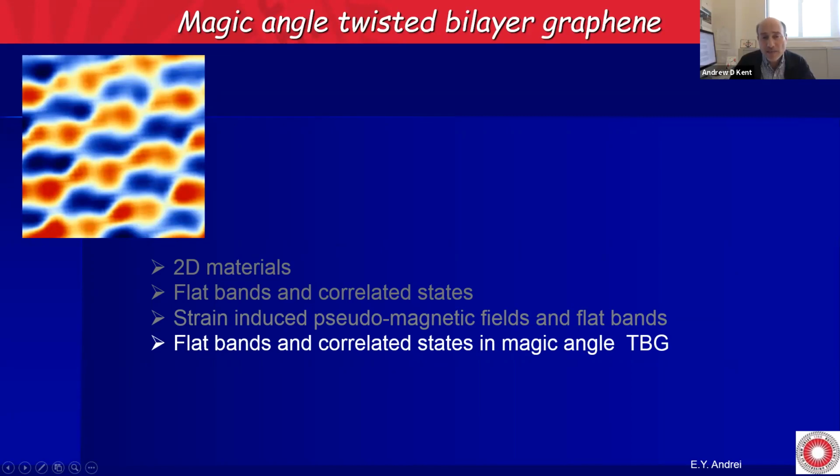Is it spatially uniform, or is it modulated? Also, does it have one period, or do you have to consider higher Fourier components? First, of course, it's not uniform. In a single sample, you get several periods, so the period changes with distance from the apex. As you go further out, the stress decreases, so the period increases. So no, it's not a single period.